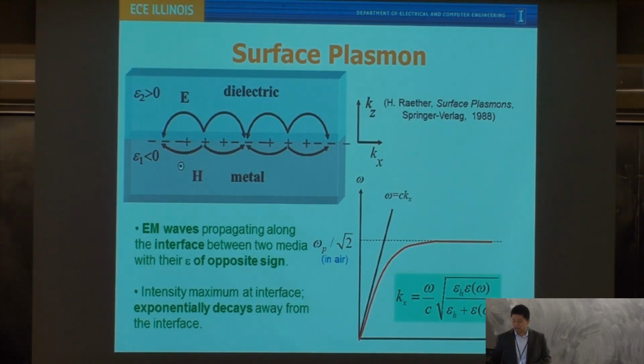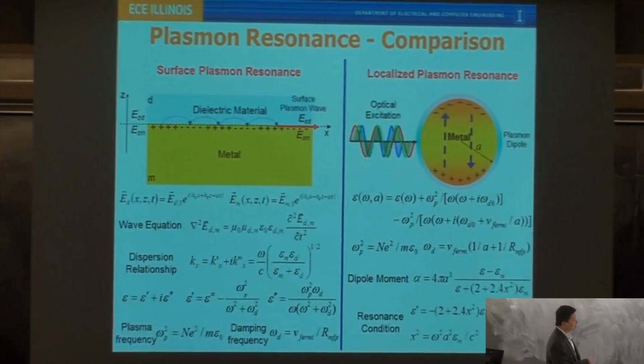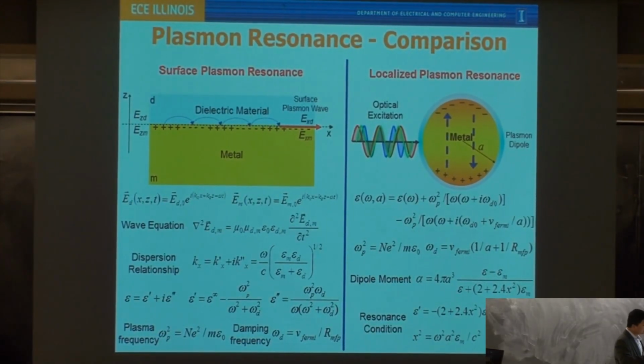But you can always circumvent that by doing nanostructure plasmonics, or nanoplasmonics. So here I do a side-by-side comparison between a surface plasma wave, that propagating wave along the interface, and a localized electron movement bounded within a metallic nanostructure. I will not go into detail of each individual equation, but as you can see, for metals, their dielectric constant or permittivity is a frequency-dependent function. And so if you change your optical frequency or wavelength, you're going to have different wave patterns on the surface. This is why we can basically confine certain modes, plasma resonance modes, within these small nanoparticle cavities.